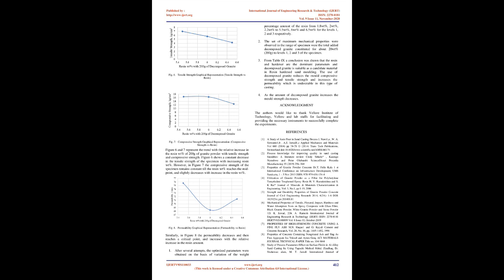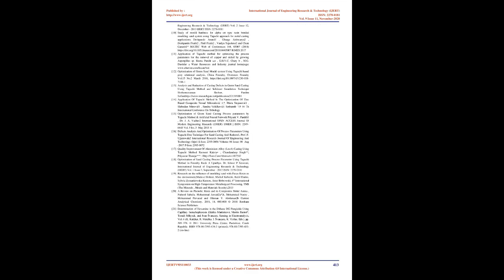With the above observation of the ANOVA table, three separate graphical representations of the mechanical properties can be obtained with the resin mixture at 20 WT% of granite powder (200 g). Figures 6 and 7 represent the trend with the relative increase in resin WT% for 200 g of granite powder with tensile strength and compressive strength. Figure 6 shows a constant decrease in the tensile strength with increasing resin WT%. In Figure 7, the compressive strength remains constant until the resin WT% reaches the midpoint and slightly decreases thereafter. Similarly, in Figure 8, the permeability decreases and then reaches a critical point before increasing with the relative increase in resin amount.